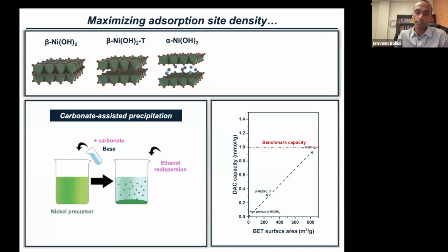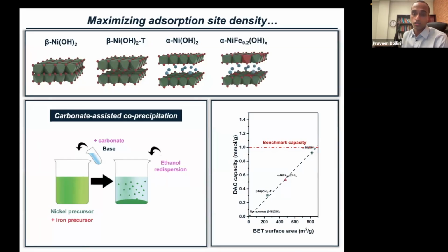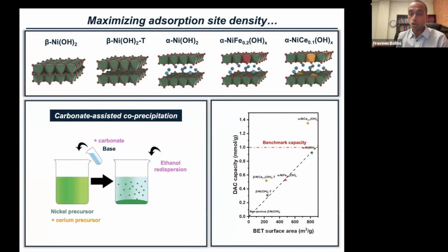Now, the surface area is not the only variable that you can tune. You obviously have different combinations of binary or ternary mixed metal oxides that you can use. I'll give you a couple of examples. You can, for example, choose iron, which is an isovalent dopant. So iron and nickel can take on exactly the same oxidation state in your oxide, and you don't change the direct air capture capacity for a given surface area value. You can judiciously choose the right dopant. So you can choose cerium as an earth abundant dopant here that can take on a valency higher than that of nickel in your native oxide, and you can increase the capture capacity compared to just the single component oxide. So again, trying to emphasize a few points here, which is that this is purely inorganic sorbent, and there's a lot of synthetic variables that you can use to improve the performance without really increasing the cost all that much.